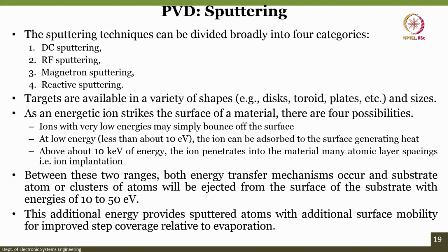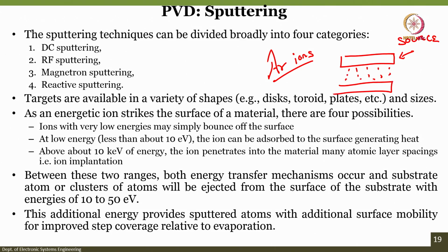This additional energy provides sputtered atoms with additional surface mobility for improved step coverage relative to evaporation. So, the point is that if I use argon, the ions will get bombarded onto the material, that is your source material, and the atoms from the source material get dislodged. When they get dislodged, they will get deposited onto a substrate, right?